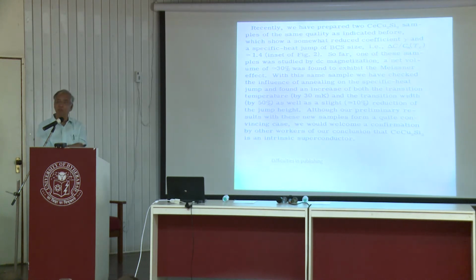So that paper was rejected by PRL a few times, and more so because at the end of the paper, today you cannot send such a paper to any journal and get it published. They say that we pressed some number of samples. We see in 5 samples this feature, not in these 5 samples. In the end of the paragraph, we prepared, in fact, I prepared more samples. At least 2 cerium copper silicon samples of the same quality as indicated before, which show a somewhat reduced coefficient gamma in their heat capacity, and a specific heat jump of BCS size. So far, one of these samples was studied for magnetization. This has some volume fraction of susceptibility. But they are not able to see it.